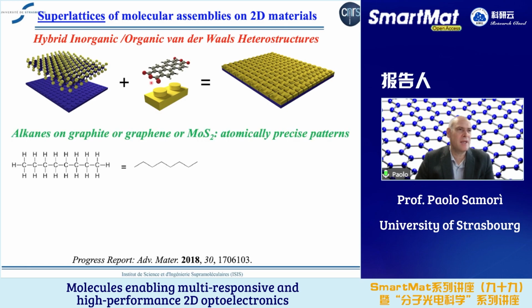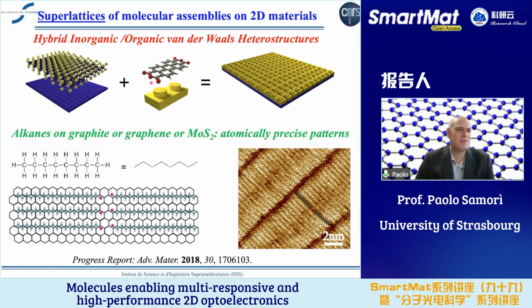Now, how can you easily create this kind of superlattice? This is very simple. You can use long alkanes, because long alkanes have a high affinity for the basal plane of graphene and MoS2, and they form lamella structures. And these are actually superlattices. So they pack along the zigzag axis, for example, of the graphene.